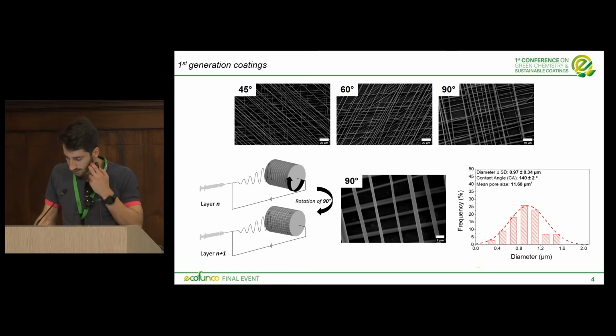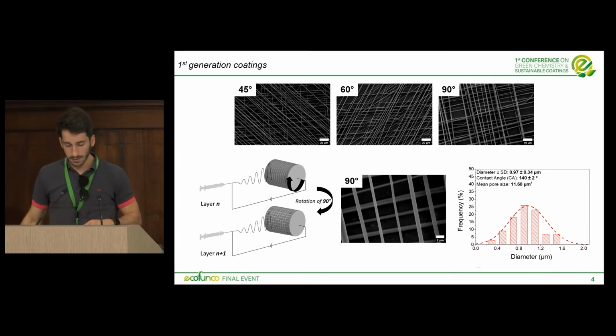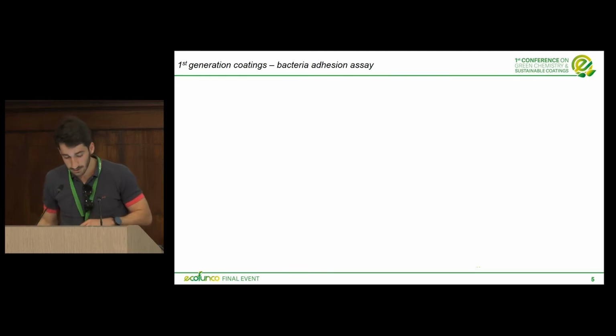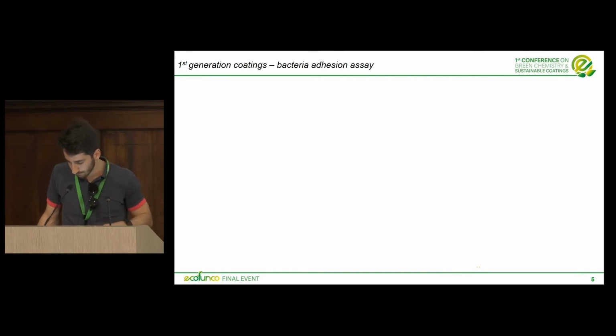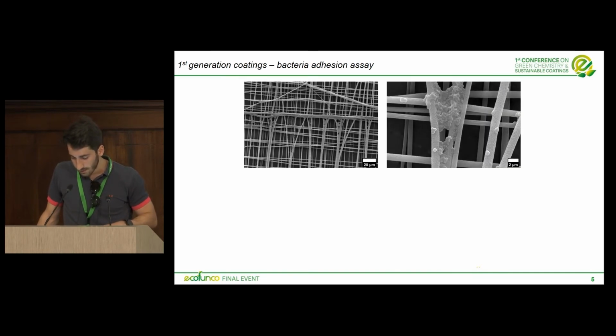Here I report a morphological characterization for the first generation samples. We have a mean diameter of around 1 micrometer, and we see that we successfully produced a super-hydrophobic coating with a water contact angle of 140 degrees. To evaluate the antifouling properties, we performed a bacterial adhesion assay considering the Staphylococcus epidermidis bacteria. The SEM images suggested that the bacteria adhere on the top of the surface and penetrate in certain points of the coating.